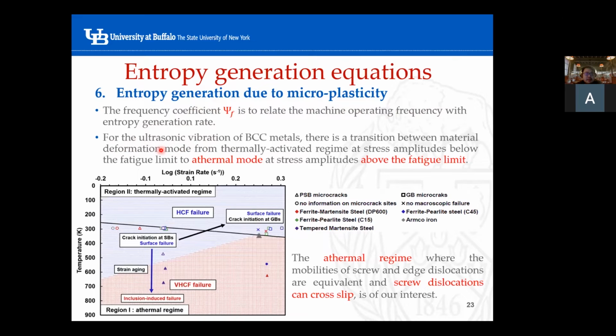Our material is basically a ferrite-based structure steel, and for ferrite-based steel with a BCC structure, we have a transition in the deformation mode from the thermally activated region to athermal mode at stress amplitude above the fatigue limit. So there's a transition between these two deformation patterns.